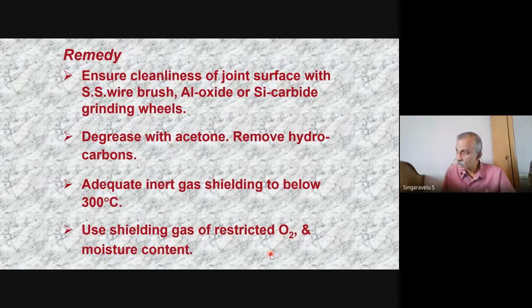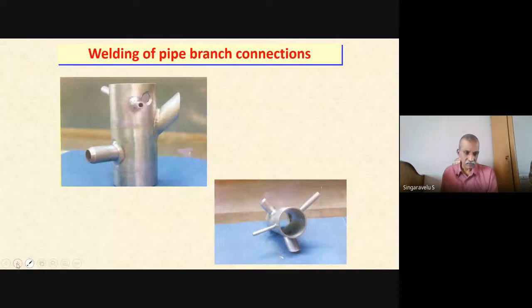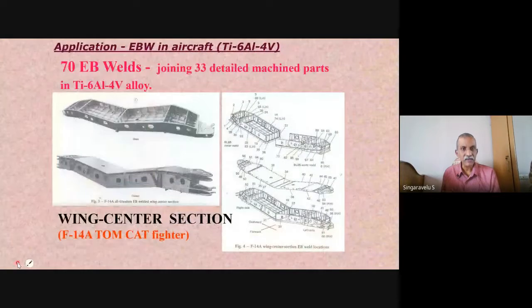The conventional TIG welding grade for steel, don't go for that. When welding titanium you go for grade 1 with restriction on the oxygen and moisture content. Cleaning, cleaning, cleaning is the only mantra for the effective welding of titanium. That is very much important. You should not touch the wire with the bare hand. It is important. This is some of the component. I think you can skip with that.